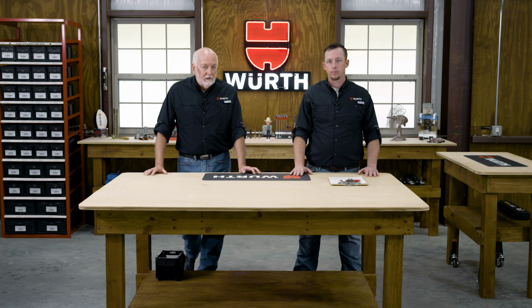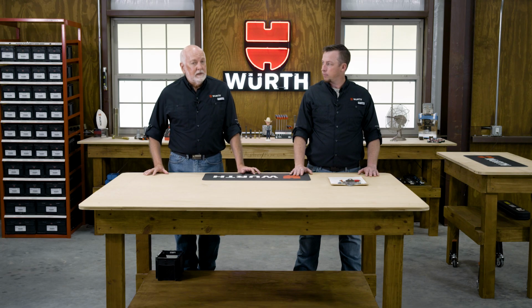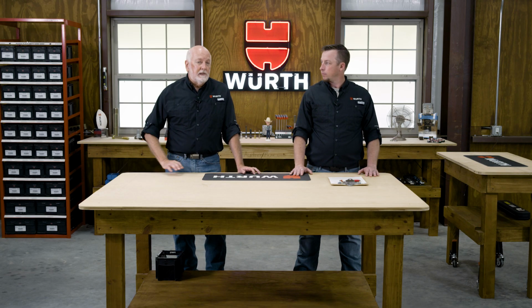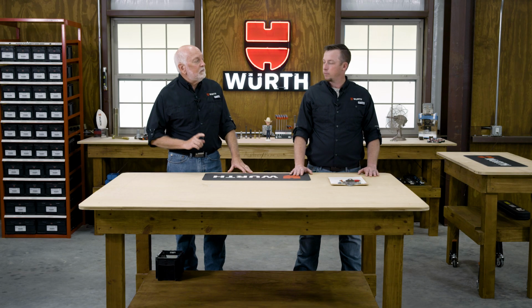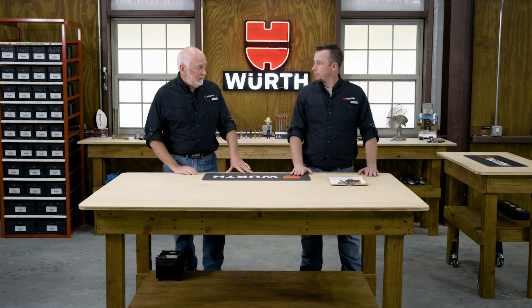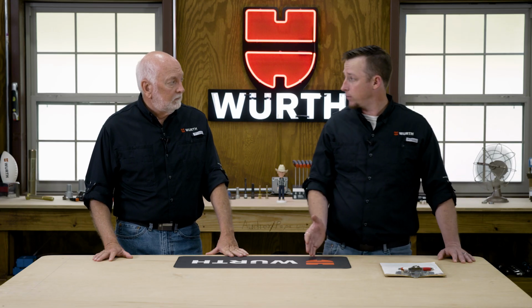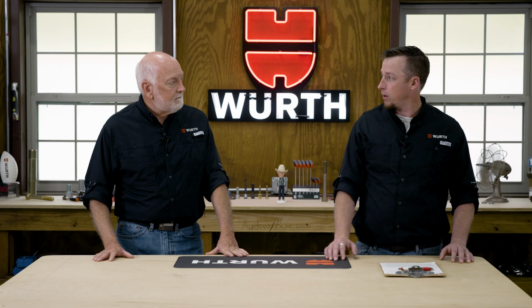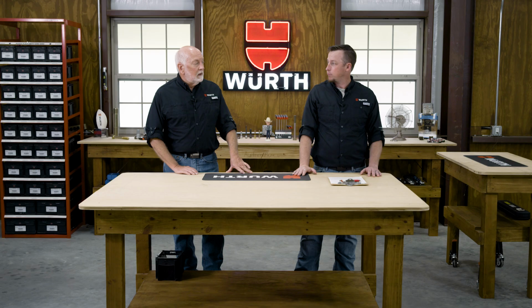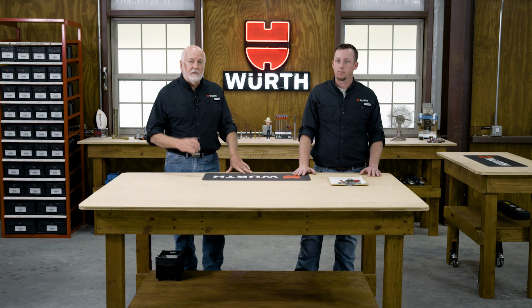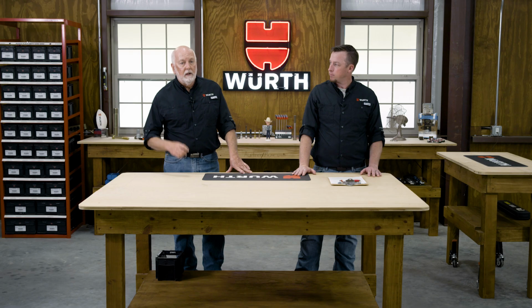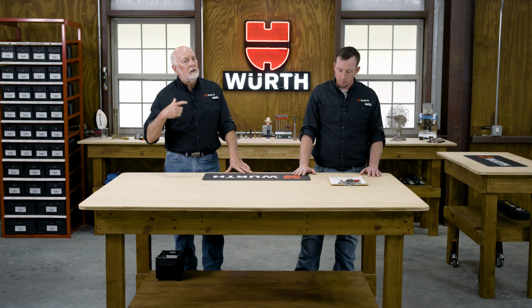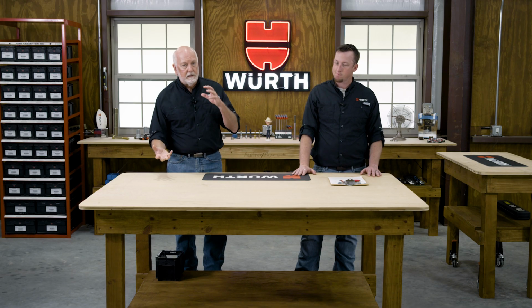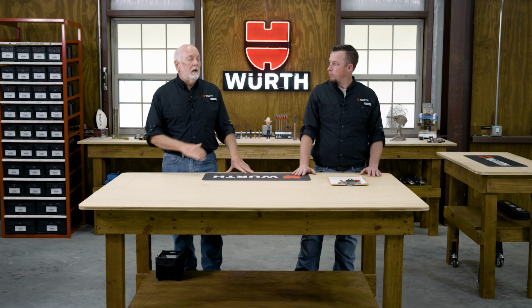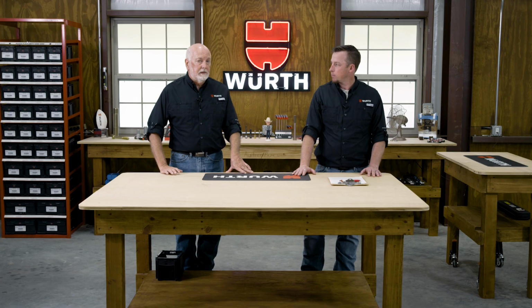So in conclusion, great corrosion resistance and environmentally sound. But Aaron, there are some challenges with zinc flake coatings. Yeah, you've got to worry about recess fill. That's where it gets inside the drive types of your screws, specifically on 6-lobe drives, Phillips drives, small diameter. In that dip and spin, if you don't get that spinning just right and get it tilted, you can come up with upwards of 3% of those recesses filled in.